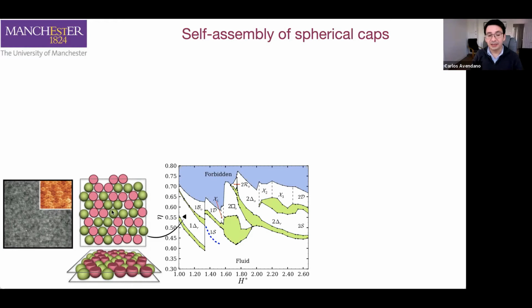The only difference now is, since the particles are non-spherical, the particles can adopt two types of orientations, either the flat facet pointing up or pointing down. And what we observe from the Monte Carlo simulations is that the population is 50-50. So we have half of the particles pointing up and half of the particles pointing down, which is exactly the same that was observed in the experiments.